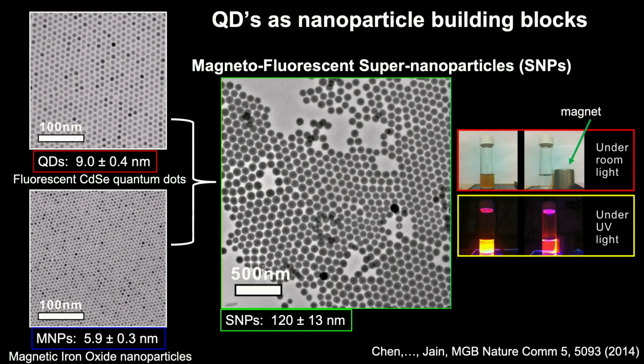This idea of assemblage also isn't confined to making big crystals of particles. Now we have two different kinds of dots here. These are the cadmium selenide quantum dots. These are magnetic particles, iron oxide particles, which are made using a very similar process, also all the same size. And it turns out if you mix these two together in certain ways, you can make super nanoparticles. These are about 100 nanometers or a little less in diameter. They're both fluorescent and magnetic at the same time because they contain both of these particles together. They react to a magnet. They react to UV light.